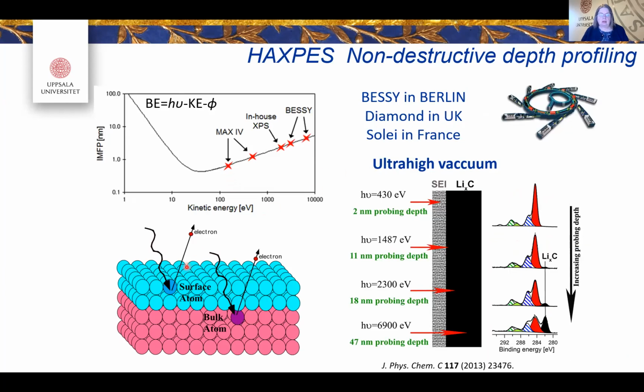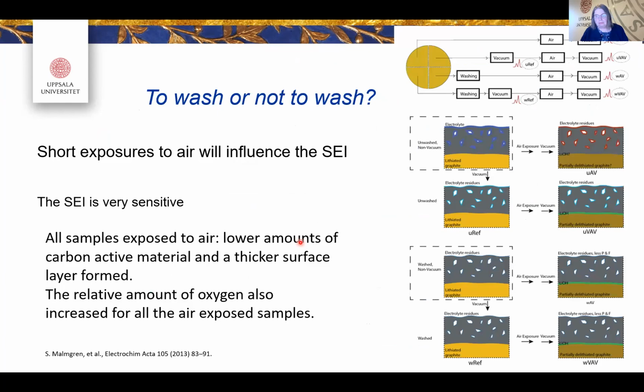I should also say, yes, of course, you can use argon etching and different etching techniques to also move away the layers and go deeper and deeper into it. But it's always risky to do that. It's actually more risky. We have done the comparison, and you get a lot of side reactions, overestimating the amounts of lithium fluoride and lithium carbonate in your results. I usually say that, based on my experience, if you have results showing a lot of lithium fluoride, a lot of lithium carbonate, you have probably had some problems in your experiments of some kind.